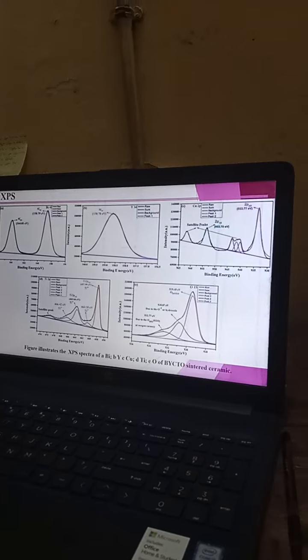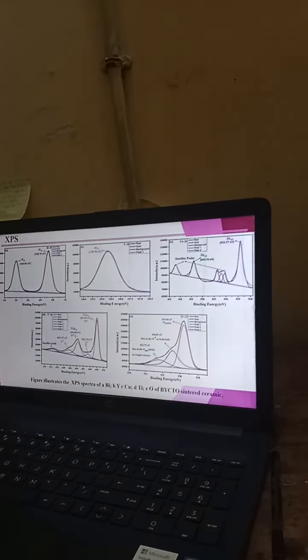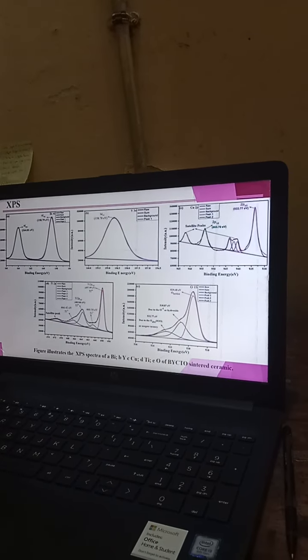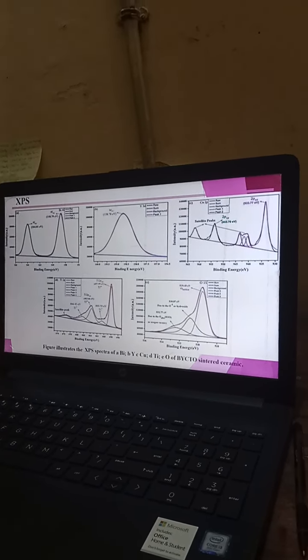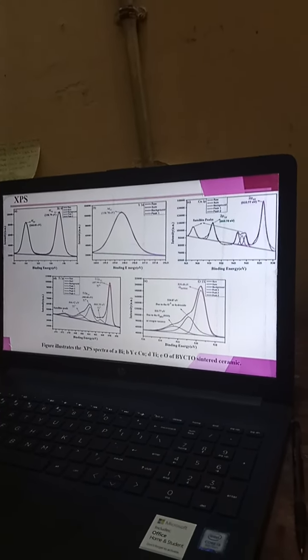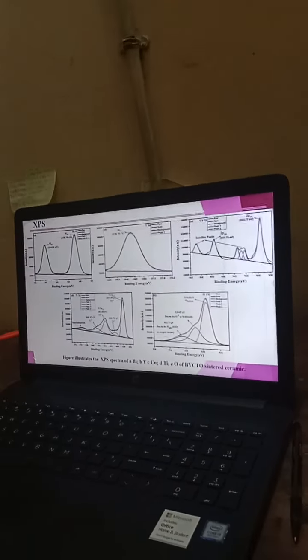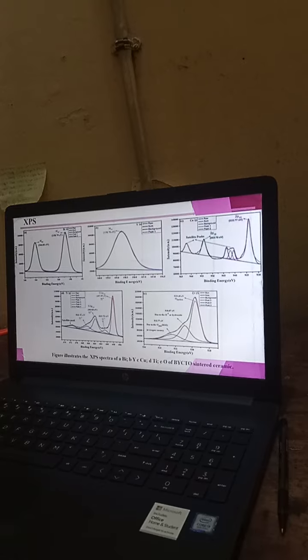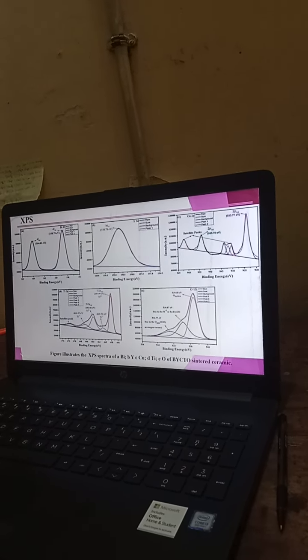Figure C presents the XPS spectrum of copper 2p. In this spectrum, we have observed several peaks, some satellite peaks and some peaks around 953.70 electron volt and 933.7 electron volt having corresponding term symbols, that indicates the copper is present in the material in plus 2 oxidation state. Figure D represents the XPS spectrum of titanium 2p. In this spectrum, there are several peaks along with satellite peaks. Each peak has individual binding energy that indicates the titanium is present in plus 4 oxidation state as well as plus 3 oxidation state. The plus 3 oxidation state of titanium in the material may have occurred due to the oxygen vacancy during the sintering process.